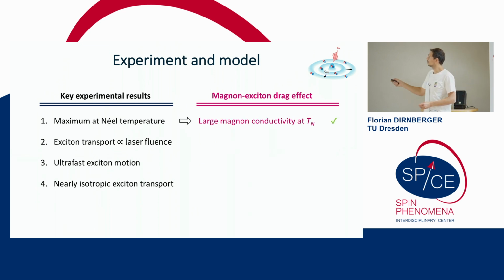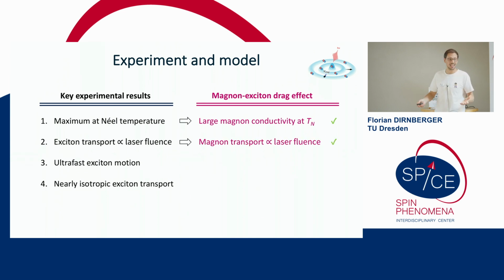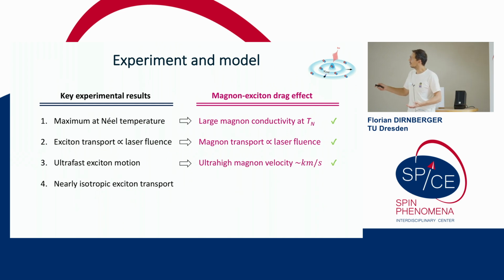So first and foremost, we observe this maximum of exciton transport at the Néel temperature, and that can be rationalized because the conductivity of magnons in antiferromagnets is very generally enhanced at the Néel temperature. So the more conductive the magnons are, the more they will accelerate the excitons. The more light we shine, the more magnons we create, and again, the more we accelerate the excitons. That explains why the exciton transport depends so much on the excitation fluence.